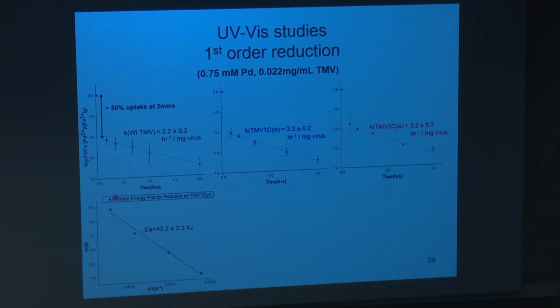And looking at the activation energy, we got an activation energy of about 43 kilojoules, which is consistent with the literature for DMAB type of reduction. And what exactly does that mean? Right now, we aren't really sure. So that was for UV-Vis.